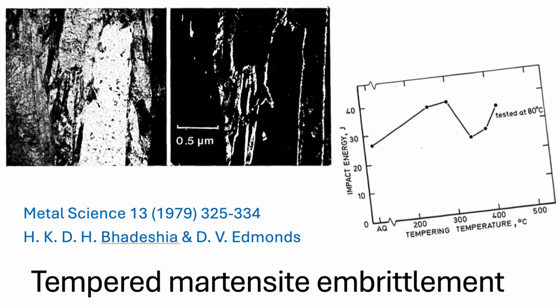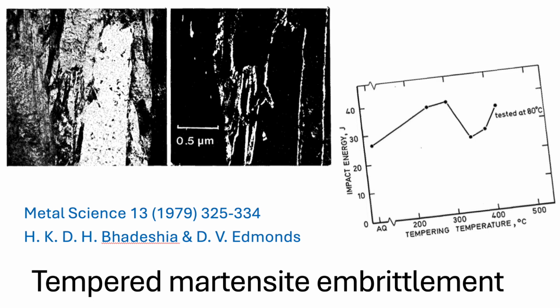Right, they don't have time to move out. Exactly. The structure holds way more carbon than it comfortably wants to at lower temperatures. It's highly supersaturated, like a sponge completely overloaded with water. Gotcha. Now, when you temper it, when you heat it up, especially into that 300 degrees C range, those trapped carbon atoms gain enough energy to start moving out. They precipitate out of the martensite lattice to form carbides like cementite.